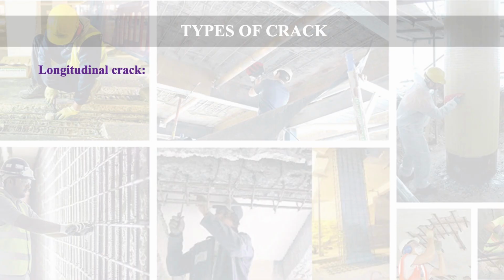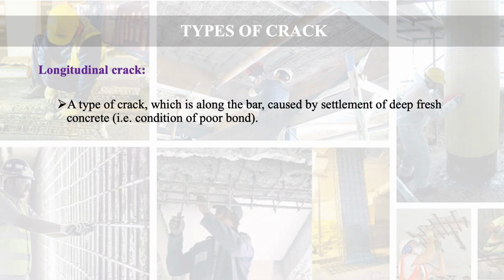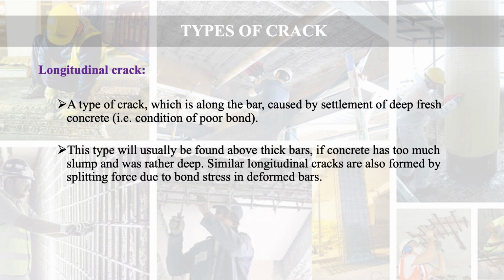Next is the longitudinal crack. Longitudinal cracks are a dangerous type of crack and these are along the bar, caused by settlement of deep fresh concrete. These are because of poor workmanship. This type will usually be found above thick bars if concrete has too much slump and was rather deep. Similar longitudinal cracks are also formed by splitting force due to bond stress in deformed bars.